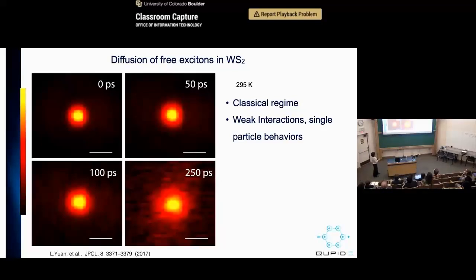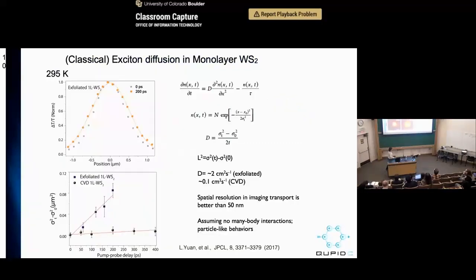As time progresses, you can see that these images broaden out. This is because the exciton has migrated out from where it was created. If you take slices of those images, you recover a series of Gaussians. At 0 time, the Gaussian is mostly defined by the pump. At later times, the Gaussian comes from the diffusive motion of the exciton. If the exciton is purely diffusive, then the solution to the diffusion equation gives you a series of Gaussians, and the diffusion constant is given by the variance of the Gaussian as a function of time. So the slope gives you the diffusion constant. This is a single particle picture, assuming no interaction between the excitons. They just diffuse around, and we can image where they are.